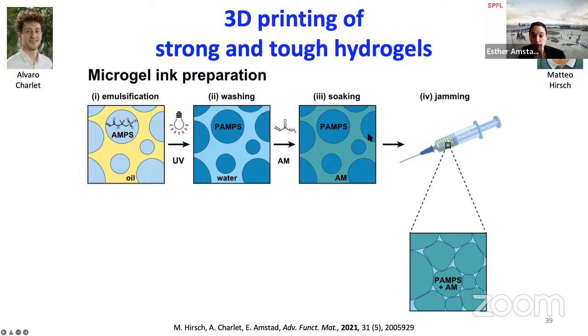Jammed is nothing else but up-concentrating them. And because these soft particles are so soft that they start to deform when you concentrate them up, they start to behave not like a liquid anymore, but like a solid, like a shear thinning paste, which actually has quite well-suited rheological properties for extrusion-based bioprinting.